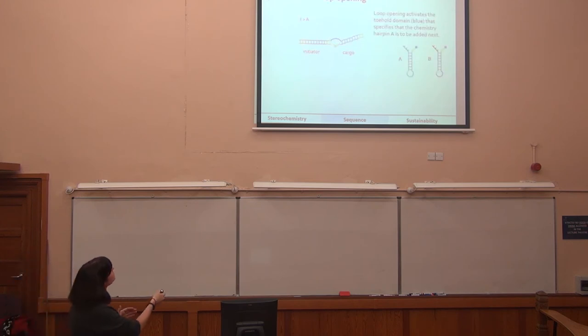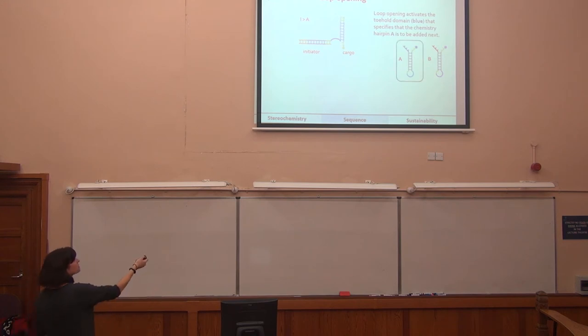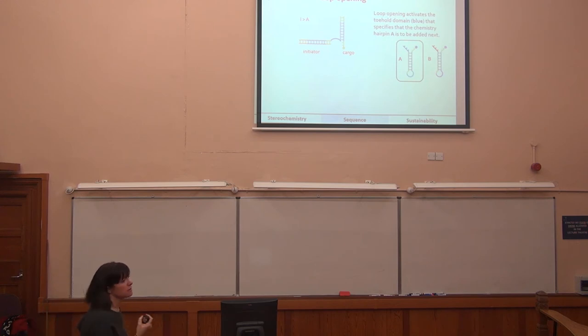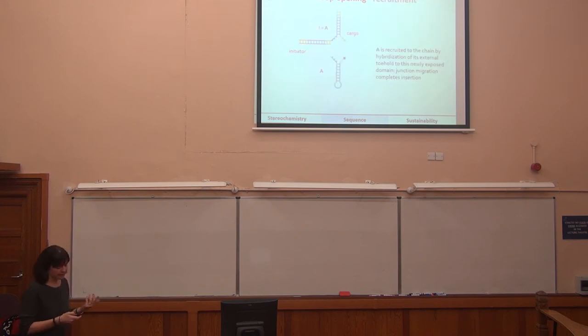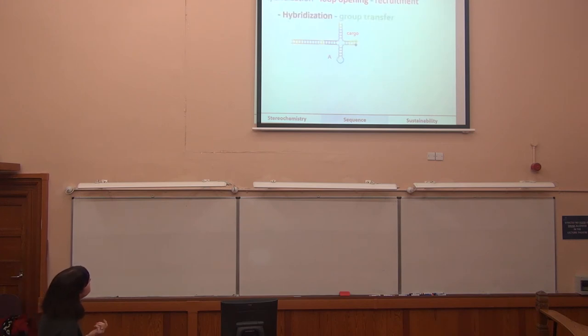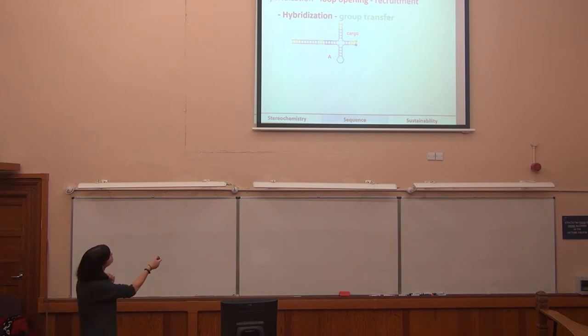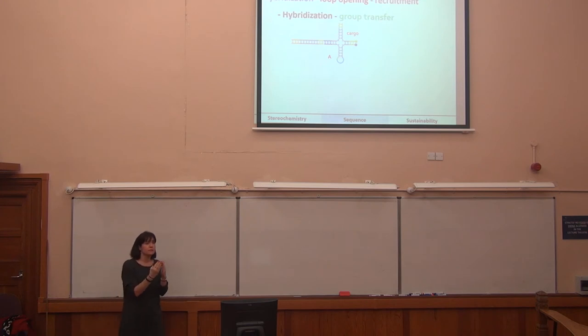And now we have this reactive hairpin. And now in solution there is this RA strand that has a complementary region, so that the molecular assembler, having opened that loop, is saying please add A next. A is then recruited. Again, you form a Holliday junction, you get hybridization, and during this hybridization and migration, you're bringing the two reactive groups into close proximity, allowing them hopefully to react.